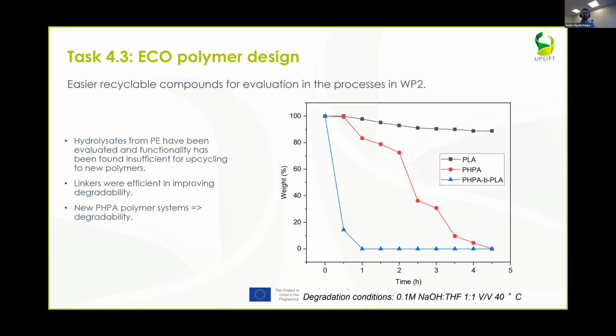This has covered a broader range of interesting building blocks. It has been looking into the use of hydrolysates from polyethylene. It has been using different types of linkers to make a block copolymer system where the entire system becomes more degradable. But what we found particularly interesting are these PHPA polymers that we found to have this very nice aromatic structure, but also a very fast degradation under mild hydrolytic conditions.